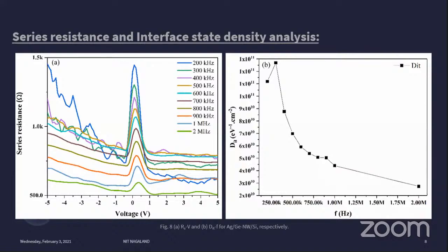The decrease in DIT with increase in frequency is because, as the frequency is increased, these surface states cannot follow the AC signal at higher frequency. The response time of these defect states is not sufficient to respond if we increase the frequency of the applied AC signal. But at lower frequency, they have the necessary time to respond to the change in the AC signal.